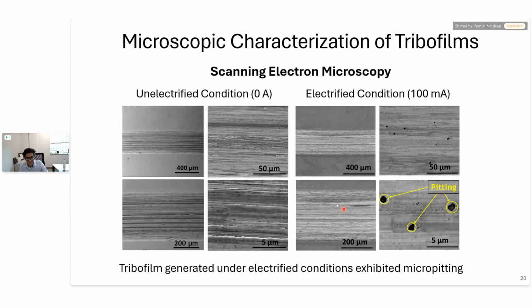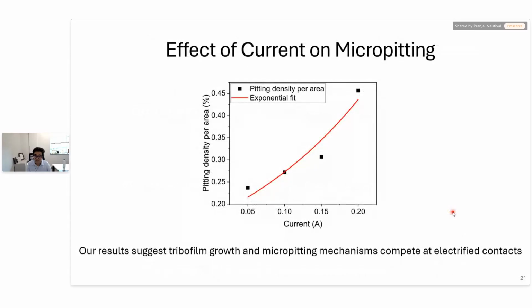At 100 milliamp, we clearly see that there is some kind of deposit on the running track, which is consistent with our in-situ measurements. But at the same time, we also saw the formation of small pits on the tribofilms. So electric fields are promoting tribofilm formation, but they're also generating these small pits on the surfaces. So we investigated these pits as a function of applied current. We looked at multiple tribofilms that we generated across test conditions, and we observed that the pitting density increased exponentially with applied current.